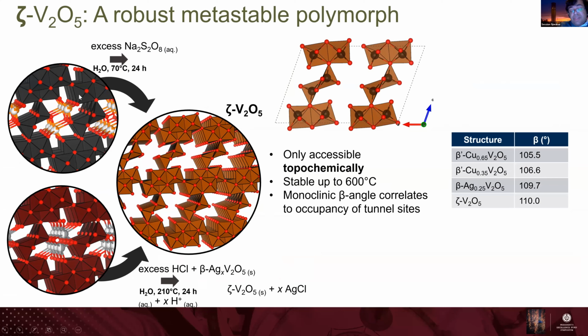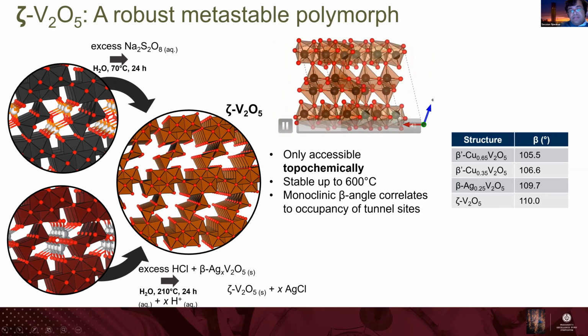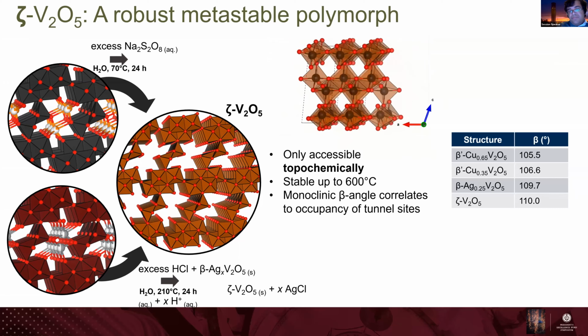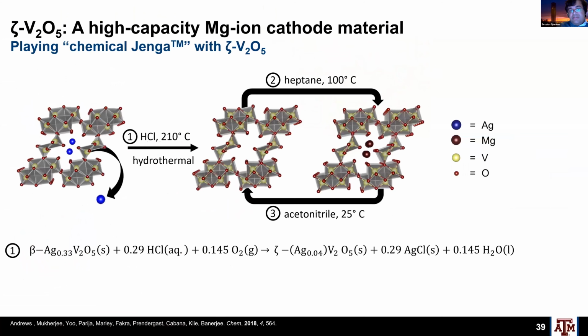So practically, this is a metastable compound, and people often think that metastable compounds are produced in trace quantities or something like that. So just to dispel that notion, we can grow single crystals of this. We can grow kilograms of this. We've got two methods. We can start with either a copper precursor, a copper V2O5, or a silver V2O5, and extract copper or silver, and we can generate this beautiful tunnel structure almost entirely emptied of the native cations.